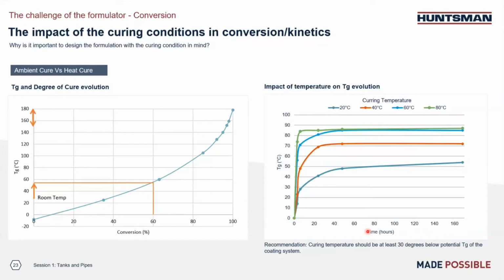Right? So if we look at the system on the left first, this is an ultimate high TG system, with the highest TG about 180 degrees C. But if we cure this system at room temperature, the TG is only about 55 degrees C, which is only about 60% conversion rate, right? This means we still have a lot of unreacted epoxy resin and curing agent left in the system, which is definitely not good for the overall performance.